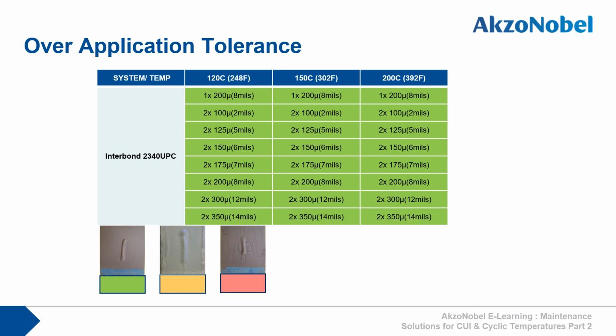This is 2340 UPC's performance in the same tests. Here you can see for all test temperatures and DFTs, there is no cracking whatsoever anywhere on the panels. Interbond 2340 UPC shows excellent tolerance to over-application.